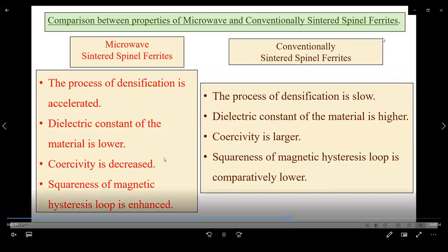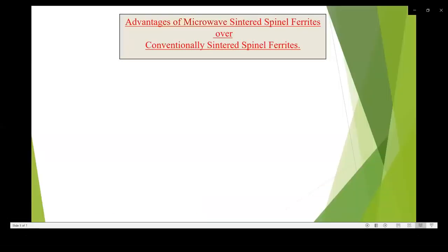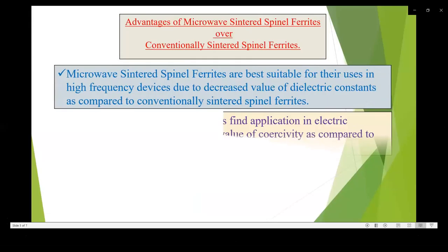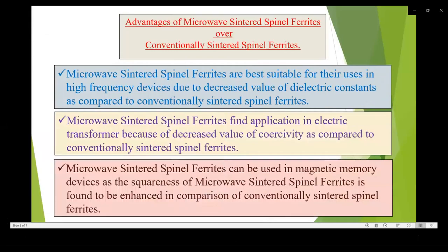In microwave sintered spinel ferrite, it has been observed that the squareness of the magnetic hysteresis loop of the material is enhanced in comparison to the conventionally sintered spinel ferrite. Here we can see the advantages of microwave sintered spinel ferrites over conventionally sintered spinel ferrites. Microwave sintered spinel ferrites are best suited for use in high frequency devices due to the decreased dielectric constant as compared to conventionally sintered spinel ferrite.